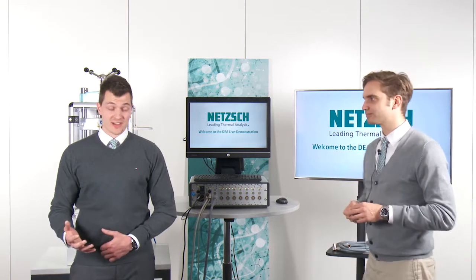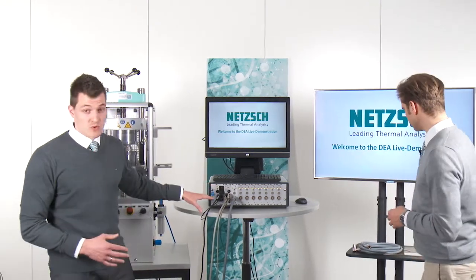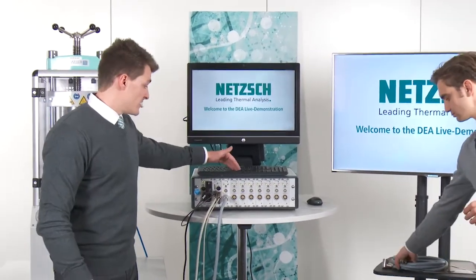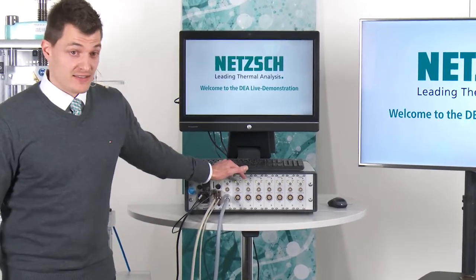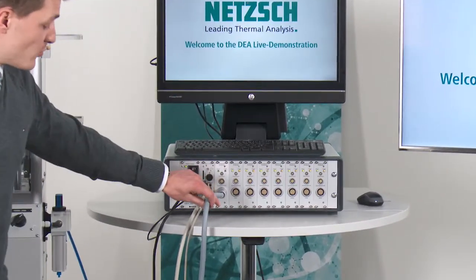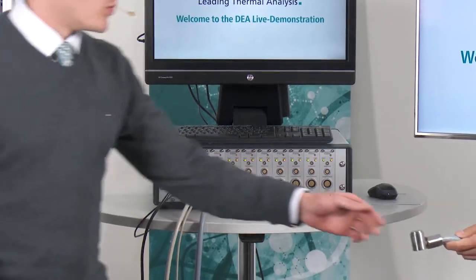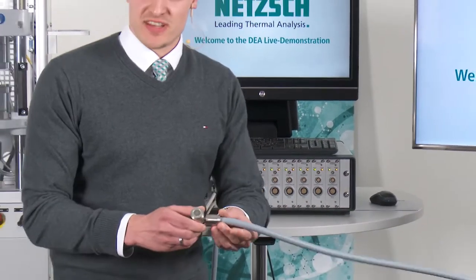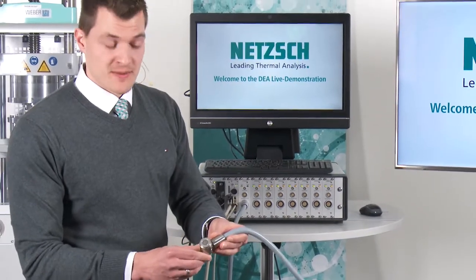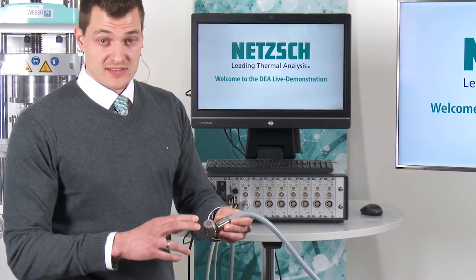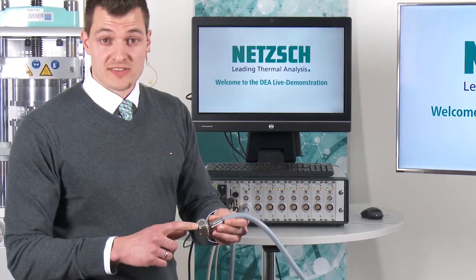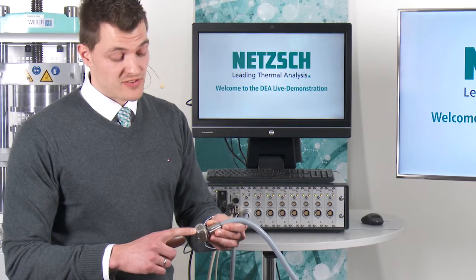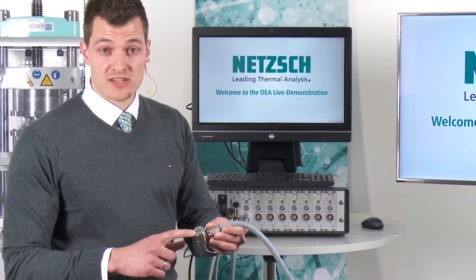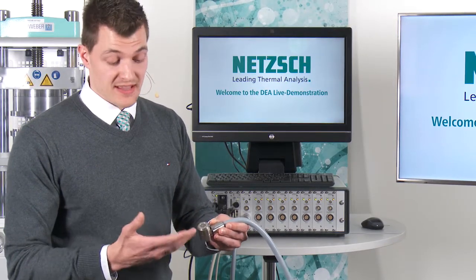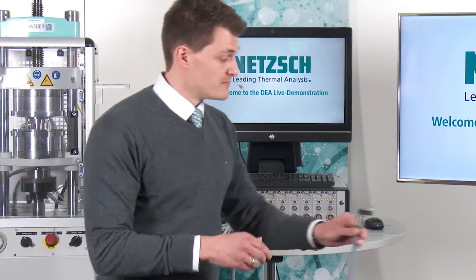Okay, so we're ready to start. Let's have a short look at the equipment we use for today. This is our NETZSCH DEA 288 dielectric analyzer. Here you can see we have one sensor plugged in channel 1. We use this type of sensor here. It's a tool-mountable sensor. The big advantage of the sensor is that we are not only recording the dielectric signal, so the curing behavior of this material, we also have a thermocouple integrated inside, so we can also follow the exothermal heat of this material during cure.